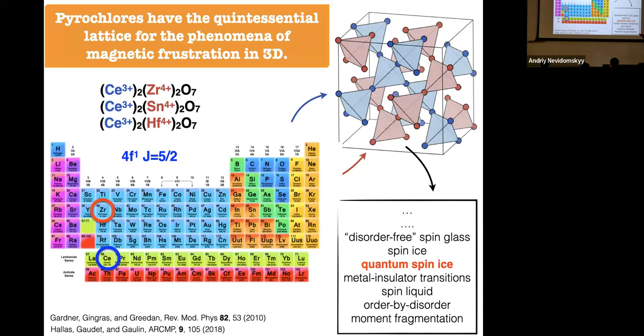And so the story I'm going to tell you about today is the story of these cerium-based pyrochlores. In these materials, all of the magnetism is connected with the cerium 3+ ion, which resides on the blue sublattice here. So these are magnetic. There are non-magnetic transition metal 4+ ions like zirconium, tin, and hafnium that reside on this interpenetrating red network of corner-sharing tetrahedra. But the red network is non-magnetic, so in a minute I'm going to forget about it. I'm just showing it to you here so you can see what the crystal chemistry looks like.